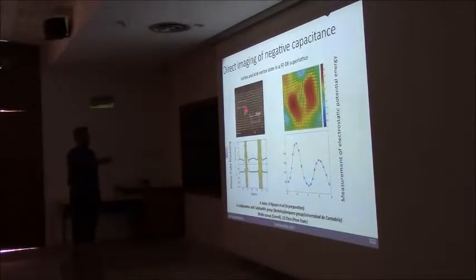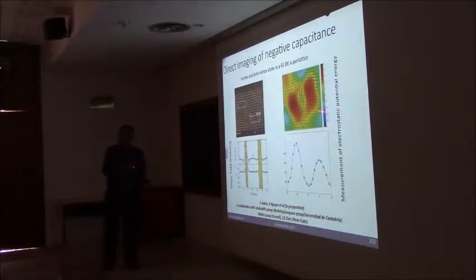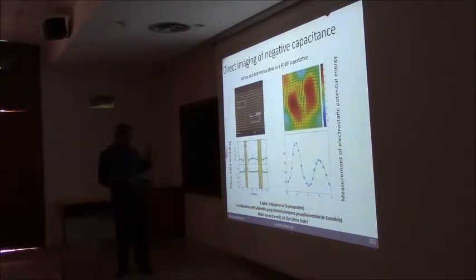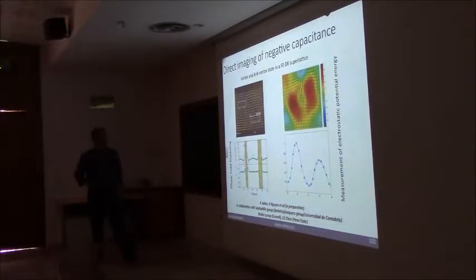So this is the same vortex, the TEM picture, structural part of it. This is work from David Muller, where they took their data, and you can map out the local distortions, and you can map out from the electric field that we talked about, from this intervention, you can work backwards, and you can get the potential energy distribution. And from there, you could calculate regions within the vortex where the capacitance is negative. So all of them seem to agree very well.